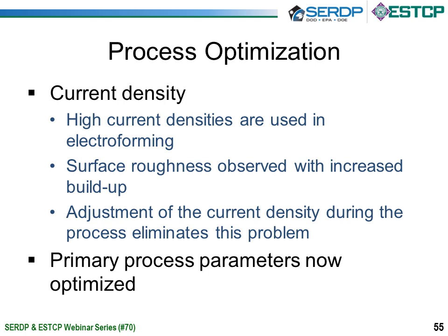So current density was the final process parameter that was looked at. Electroform processes typically use very high current densities. And initially, for low deposition thicknesses, there really wasn't a whole lot of effect. But as it started to get around 5 to 10 millimeters thick, and you can correct me if I'm wrong here, John, roughness became more of an issue.